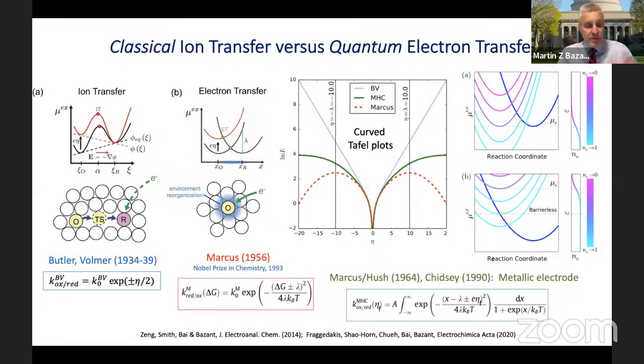And essentially, he developed a theory of that, which led to quite a different dependence, where the dependence on the free energy change, or the overpotential, if you will, is actually more of a Gaussian shape instead of a simple exponential. And a parameter lambda called the reorganization energy comes in. And that's because the picture is that it's not that an electron goes over some barrier to the other side. Instead, the initial and final states of the electron are fluctuating such that when they both fluctuate to a similar energy, the electron just tunnels immediately and isoenergetically to the new state.